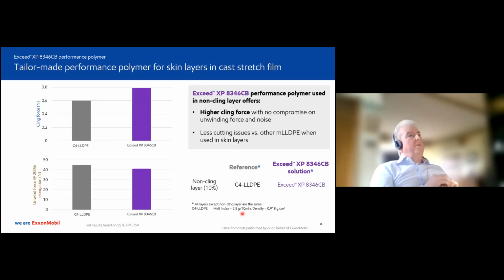Okay, now another very interesting property of this grade is that you can use it in a non-cling layer. And what we found is it actually promotes cling in the opposite layer. At the same time, the unwinding force is lower. And you can see those examples here, where we're using C4LL as the resin in the non-cling layer. Now, the reason why I've used the C4LL as a reference is because we are typically targeting here hand wraps and machine wraps, which would tend to use those sort of grades, but obviously other grades could be used.